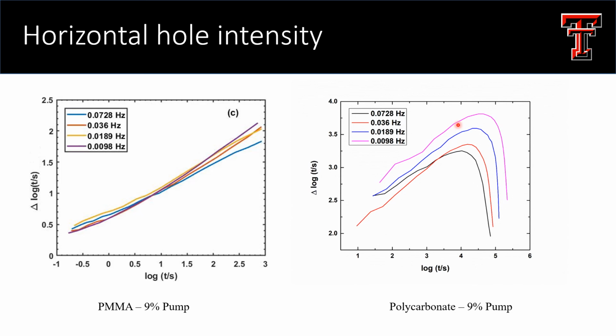Peak intensity dependence on pump frequency is related to the relaxation time or the molecular mobility. Molecules whose relaxation time is the same as the time period of the pump can only be modified in a hole burning event. In the glassy regime, molecules usually exhibit large relaxation times, and therefore lower pump frequencies can modify a greater number of molecules. Hence, higher peak intensities are observed at lower frequencies.